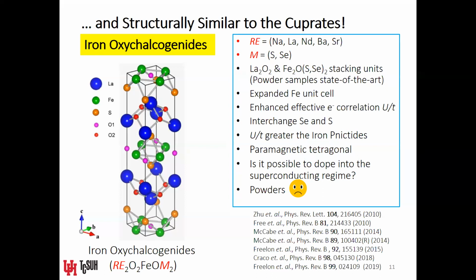And this is a strong Mott insulator, okay, to begin with. So at high temperatures, it has a tetragonal paramagnetic phase, as in the case of the pnictides. And this material was brought up a couple of years after the report of iron-based superconductivity as a candidate for an iron-based insulator that might be driven into superconductivity. And so I have a mistake on this slide because I have the sad face at the bottom bullet, but the sad face should also be at the bullet next to last.